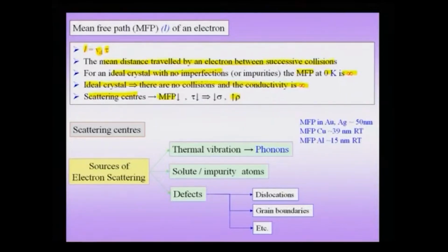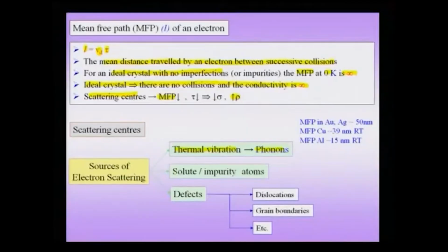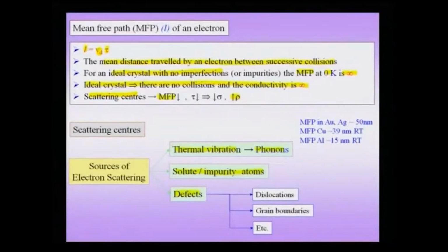Now, what is the origin of these scattering centers? One is obviously thermal vibration. If there are atomic vibrations, the collective quantized modes of these vibrations are called phonons, and if an electron suffers a collision with a phonon, its velocity can be reduced to 0. The second origin of scattering centers is solute or impurity atoms. When I say impurity or solute, it could be a substitutional element intentionally added, or an unintentional element present in any material. These impurity atoms distort the lattice, causing an imperfection, and can act like a scattering center for the conduction of electrons. Further, a crystal could have additional defects like dislocations, grain boundaries, stacking faults and other defects, which also can act like scattering centers for these electrons.